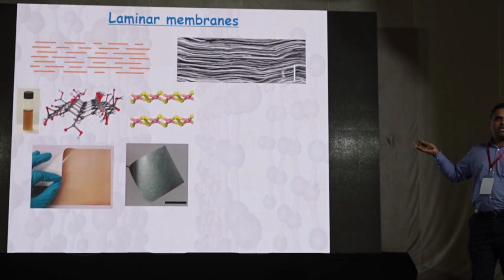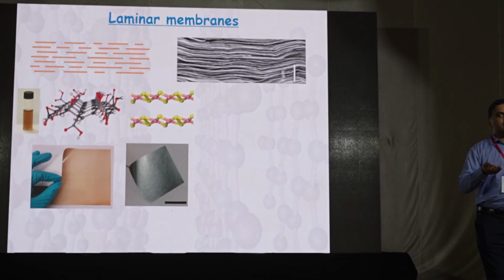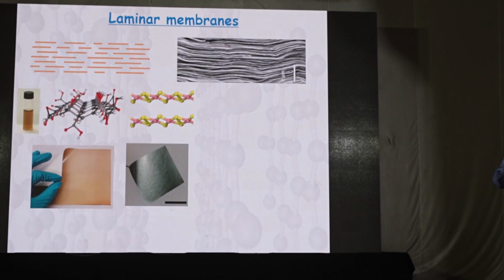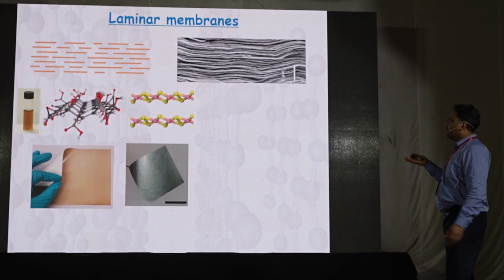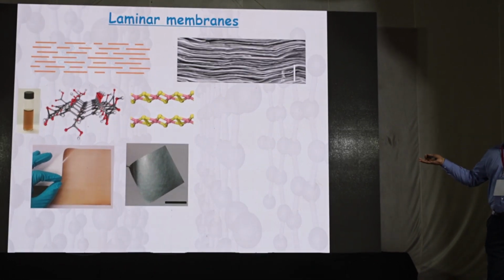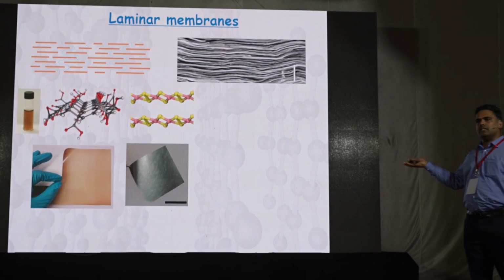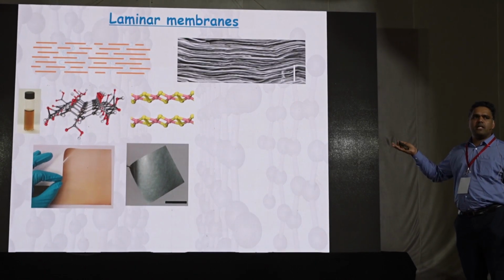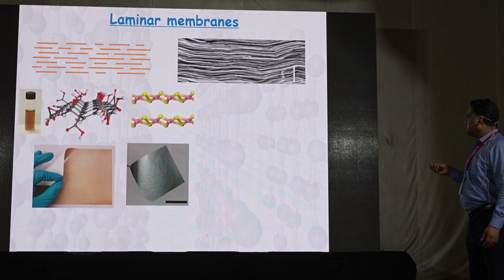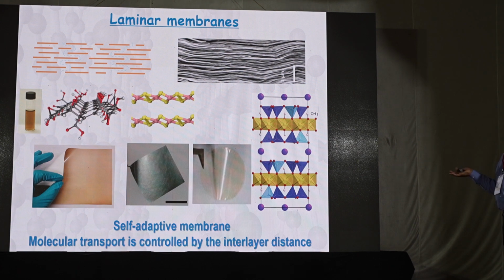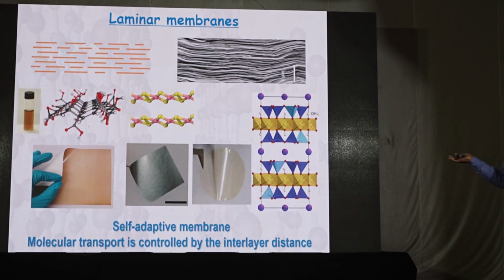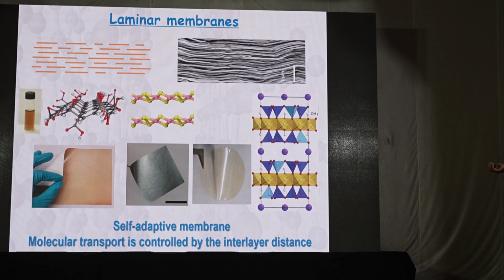There is one reason why I use graphene oxide: because it is hydrophilic, it can be dispersed in water, it is very easy to make in large quantity, and it is industrially scalable. You can use molybdenum disulfide, again similar to graphene oxide. You can get it into water. In any chemistry lab, you don't need any special facility to make any of these materials. You can use other types of material like clay. Again, this is a cheap material, available everywhere. It's called vermiculite or even mica, or any kind of clay-based material can be exfoliated into monomolecular layers and then restacked for membranes.